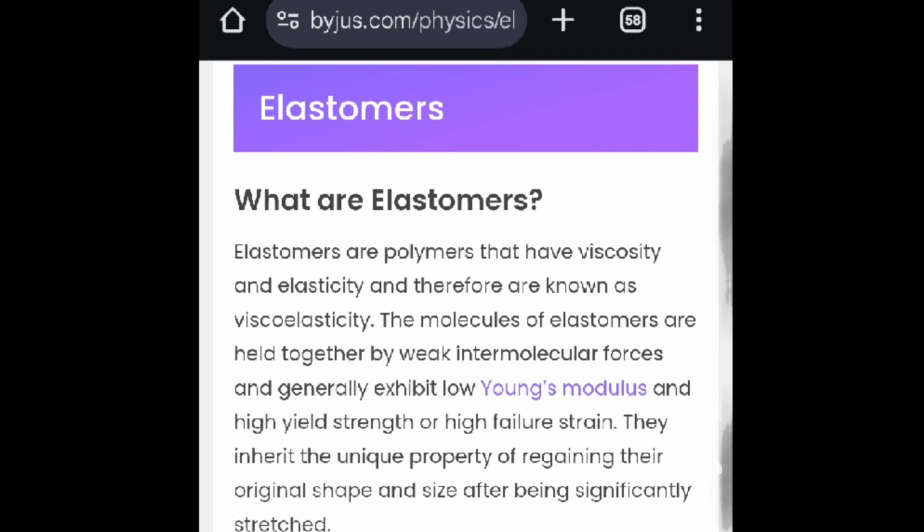People have confused the fact that SBS contains a portion of a compound that is in itself elastomeric, but when combined with the other ingredients, the final result generally isn't. The other flip side of that equation is that, like I said earlier, some of the adhesives, mostly for cold application, but some of the adhesives used, can qualify as elastomeric, but never the membrane itself.